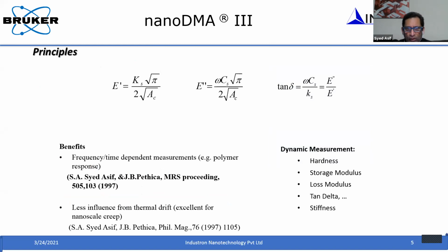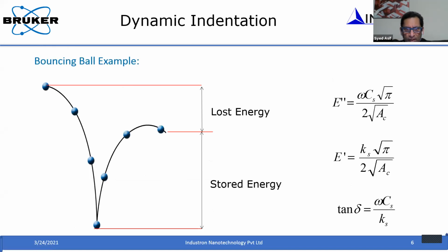In both techniques, what you measure is the stiffness. In a dynamic technique, along with the normal stiffness that you measure, you also measure the loss component of the stiffness, depending upon the damping of the material. And if you take the ratio of the storage stiffness and the loss stiffness, you get tan delta, which is characteristic of the damping of the material. Okay, so it is very useful for viscoelastic materials.